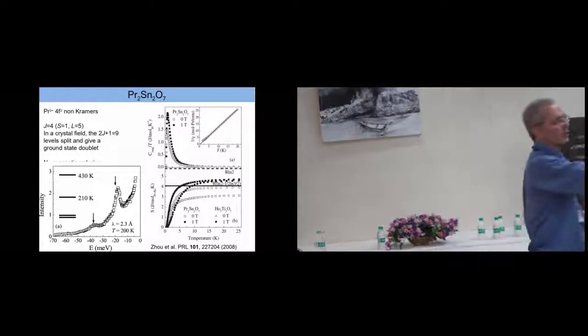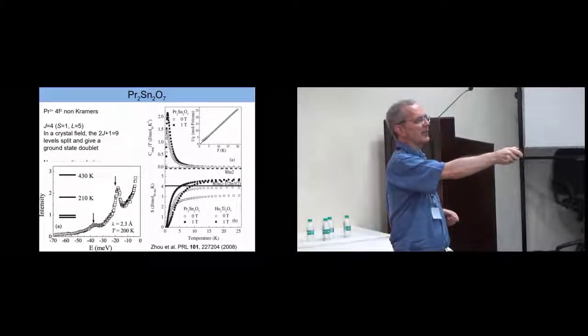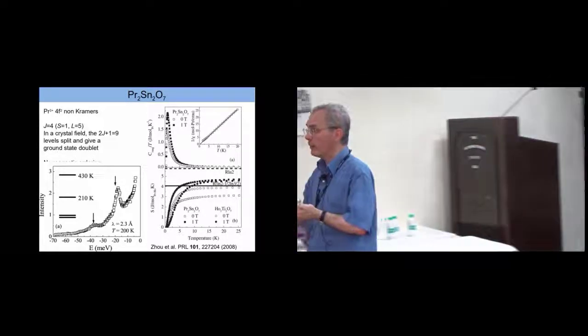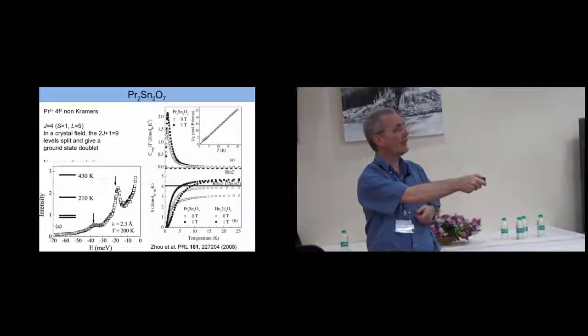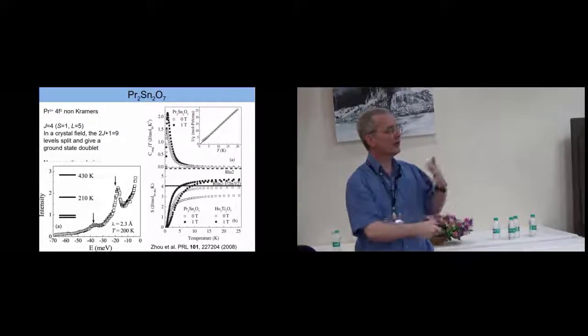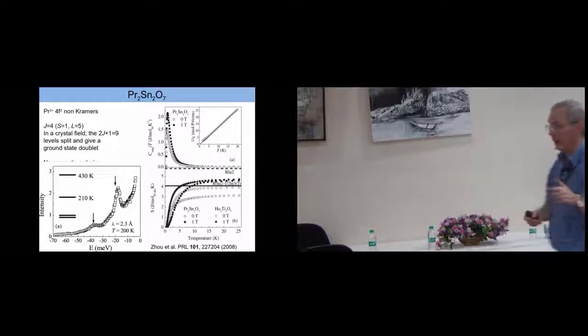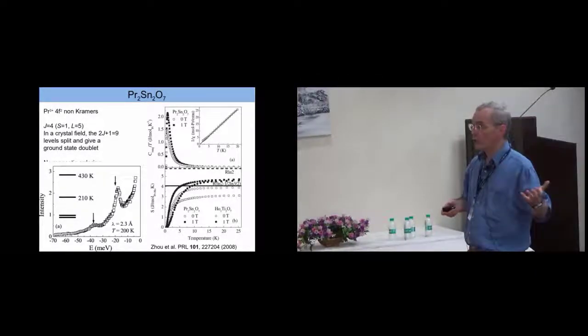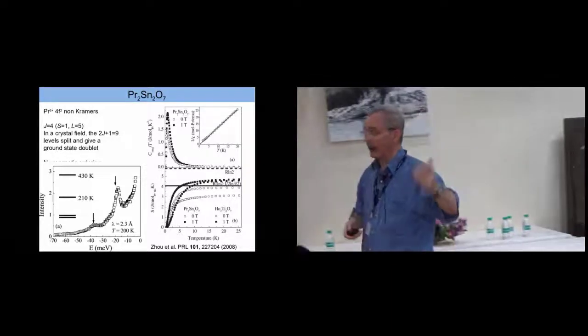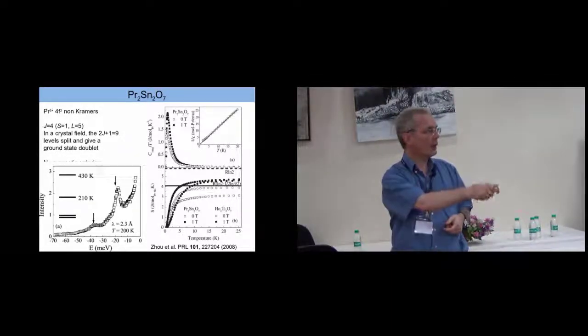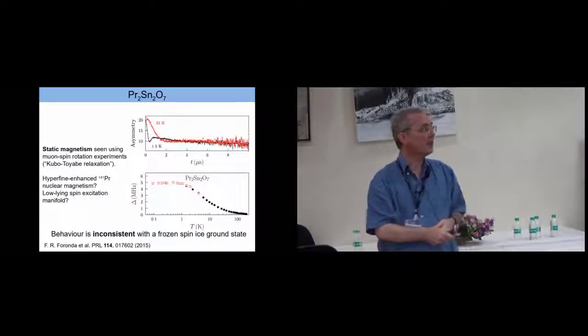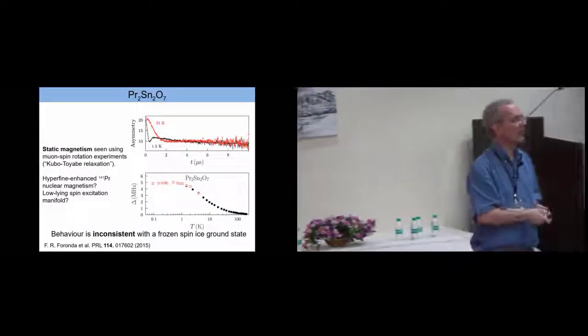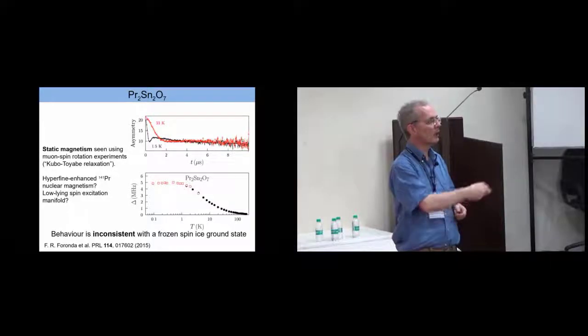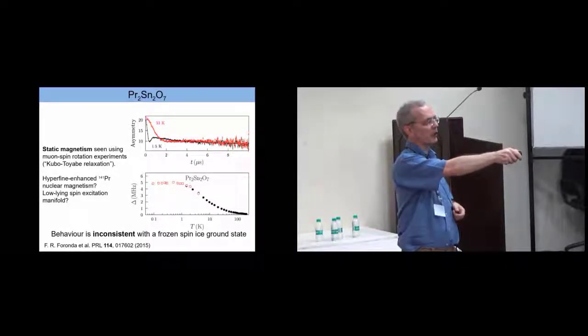More recently, people have got interested in this compound, praseodymium stannate. It's also a spin ice material, but the praseodymium ion is non-Kramers. It has a 4f2 ground state, and this gives you a ground state doublet. So this is a spin-half material, effectively, in contrast to dysprosium titanate, which has a very large spin. Now, the properties of this material show spin ice-like behavior. We did some muon measurements on it, and we didn't see spin ice behavior. We saw something that looked like static magnetism. We saw what in the muon community is well known as a Kubo-Toyabe relaxation, which actually goes all the way up to high temperature.